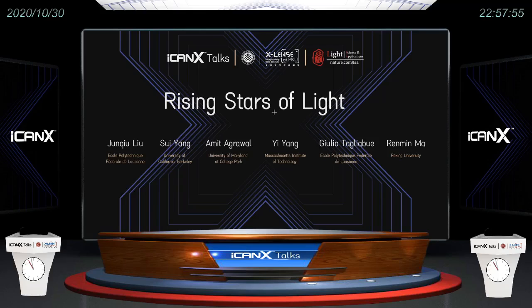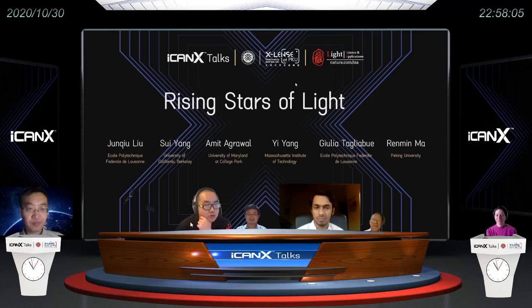And also, I want to comment on one of the questions from Amit, that the judge asked about super resolution from a metasurface. So I would say that if you can couple the metasurface with a high refractive index soft metamaterial on top, that will give you high k immediately on the surface. So that will eventually generate high resolution, super resolution imaging. So that's one of the things that we can easily utilize this soft metamaterial for in real applications for imaging.